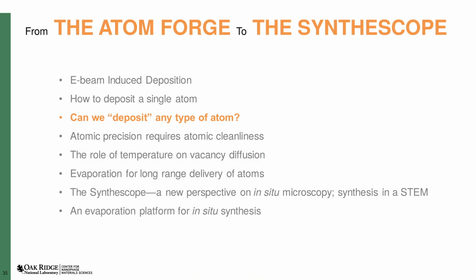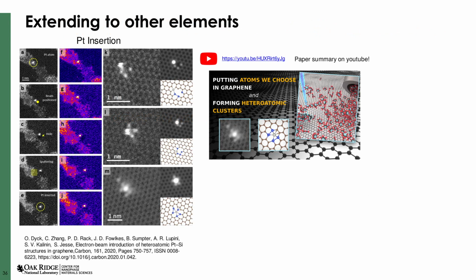But how about other types of atoms? The silicon atoms were just found on the graphene surface. Maybe we can put atoms on the graphene surface that we want to put in the lattice. The first element we tried was platinum. We used e-beam to deposit platinum lines with an SEM, and then found some platinum atoms in the surrounding contamination, and were able to attach them to the graphene defect sites created by the e-beam.